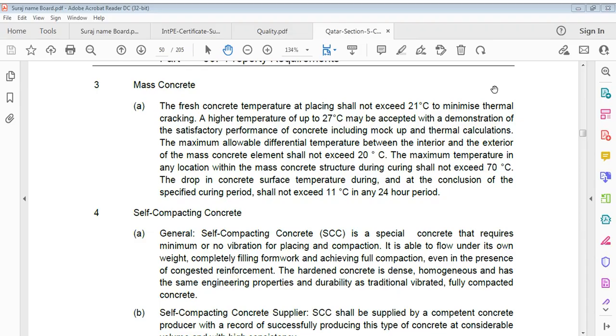That's another point, the differential temperature in mass concrete. Internal and external temperatures should not differ by more than 20 degrees Celsius. In any location of that mass, it should not exceed 70 degrees Celsius. Internal temperatures are higher in this case, and external is dependent on weather conditions. The drop in concrete surface temperature at conclusion of the curing period should not exceed 11 degrees in 24 hours. That is the drop in concrete temperature.